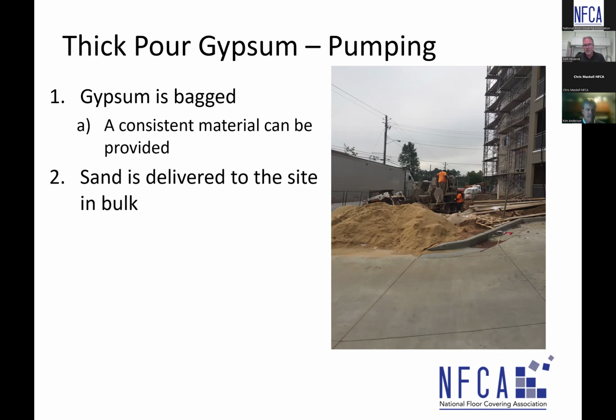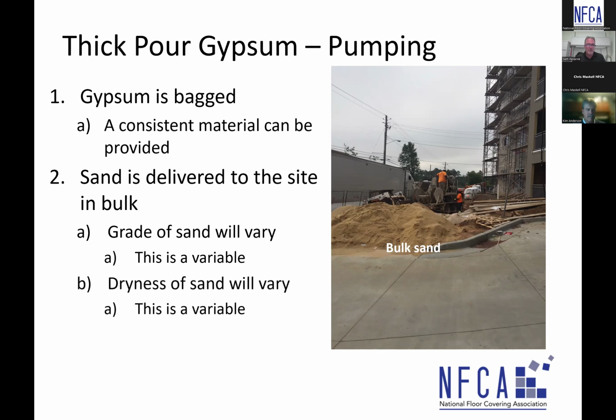The sand, however, as I said, is trucked to the site and dumped on site, and that can be a variable. The grade of sand will vary, depending on where you're located and where they got the sand. The dryness of the sand will vary, depending on how wet or how dry it was when it was delivered to the site. And certainly if Mother Nature happens to decide to throw some rain into the equation, it'll change the dryness or the wetness of that sand. This is different from a bagged product that already has the sand in there, where the sand is a very specific sand. So the sand that's delivered to the site is certainly a variable in the equation.